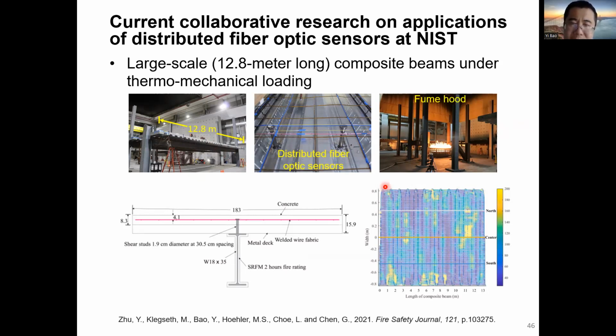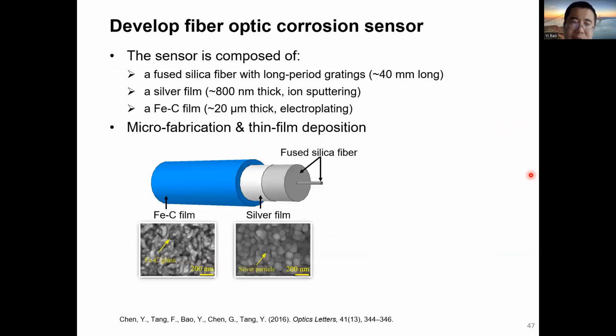So we did this thermomechanical analysis. We burned the specimen in fire. At the same time, we applied the mechanical loading to the specimens. So we were able to measure the temperature and the strain change of the composite specimen.